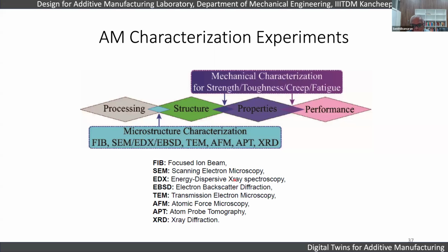XRD is a very low-cost technique for measuring residual stresses on the surface. If you want to measure subsurface residual stresses, you can go for expensive methods like neutron diffraction and other methods where you could measure the subsurface residual stresses. So you have to employ these characterization methods to validate your scale-to-scale transformation of the property to function. And also you have to use mechanical characterization to basically qualify the process to structure relationships, right? So these are all to be used.